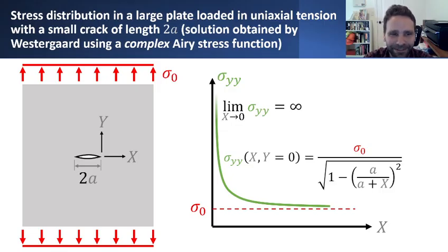It's a limitation in the way that we've come up with these elastic assumptions in the relations between stress and strain. Really, there should be some kind of plasticity or some kind of more complicated material behavior going on. But to come up with analytical solutions like the one shown here that account for plastic deformations is practically impossible. At least you could come up with good approximations using numerical methods, but at the time that these solutions were developed, such methods were just not available. Nonetheless, it's worth taking a look at this particular solution, even noting the deficiency that this is not a physical result, that the stresses will truly not be infinite in the vicinity of the crack tip.